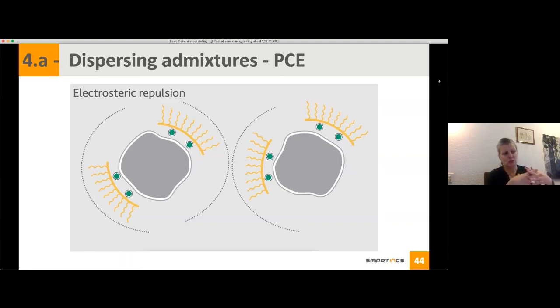Why are PCE so powerful compared to the other admixtures? It's because the PCE have these side chains, and this is not the case in the other superplasticizers. The naphthalene and melamine also adsorb on the surface of your particles, but then you will have electrostatic repulsion. So you will have repulsion dispersion, but it's not as strong as when you have the side chain, then you really have something physical. So you have electrosteric repulsion, and it's more performing than only electrostatic.